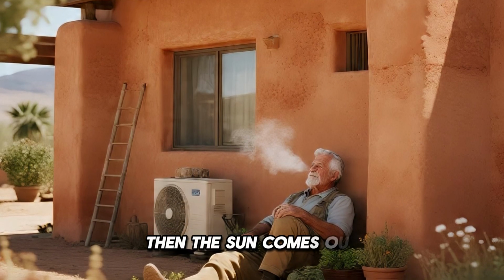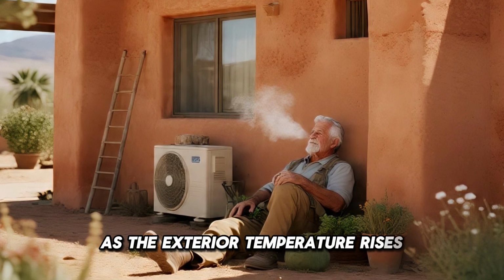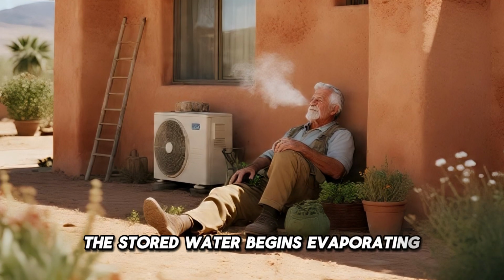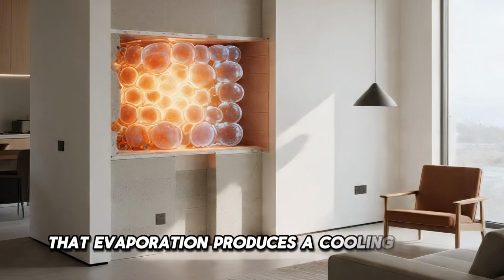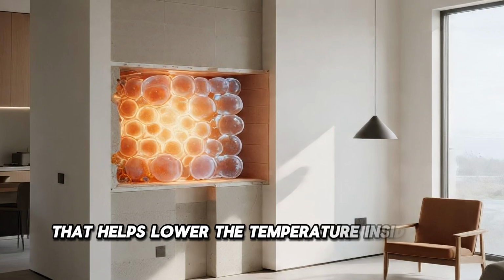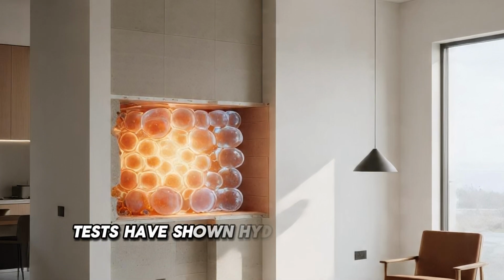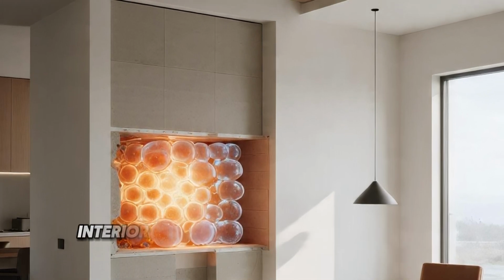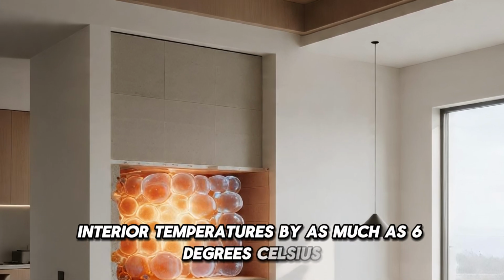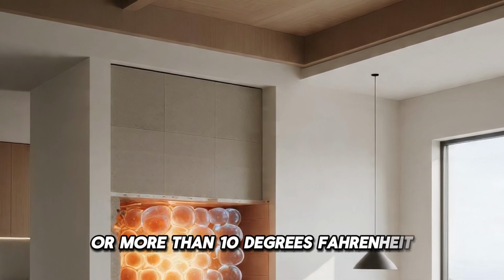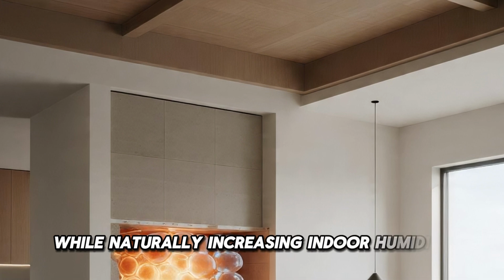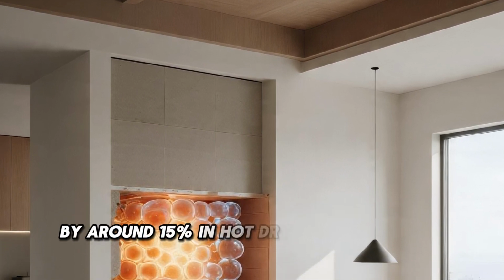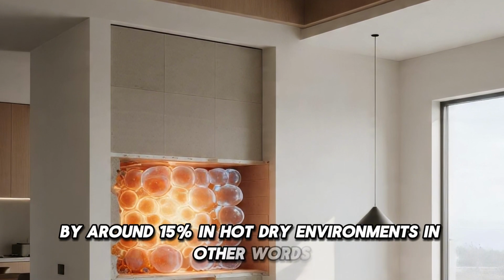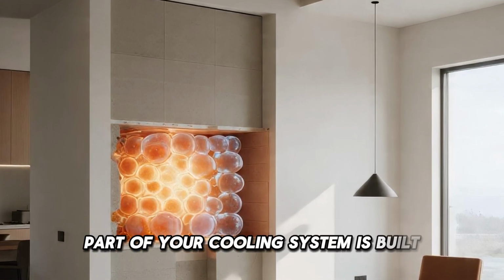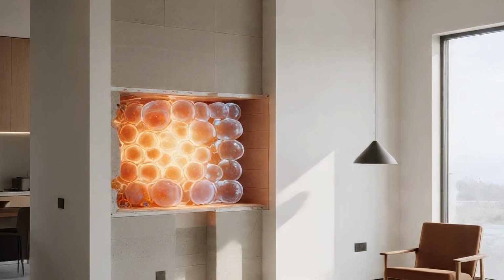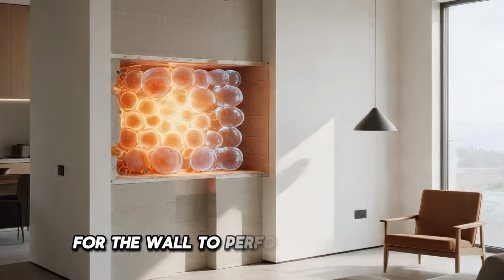Then the sun comes out. As the exterior temperature rises, the stored water begins evaporating. That evaporation produces a cooling effect that helps lower the temperature inside the building. Tests have shown hydroceramic walls reducing interior temperatures by as much as 6 degrees Celsius, or more than 10 degrees Fahrenheit, while naturally increasing indoor humidity by around 15% in hot, dry environments. In other words, part of your cooling system is built directly into the clay itself. No compressor is required for the wall to perform that function.